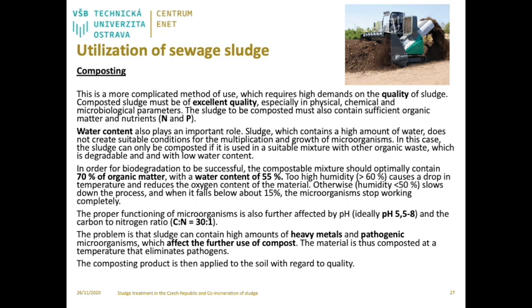Sludge, which contains a high amount of water, doesn't create suitable conditions for the multiplication and growth of microorganisms. In this case, the sludge can only be composted if it's used in a suitable mixture with other organic waste, which is degradable and with low water content. In order for biodegradation to be successful, the compostable mixture should optimally contain 70% of organic matter with a water content of 55%. Too high humidity causes a drop in temperature and reduces the oxygen content of the material. Otherwise, it slows down the process. And when it falls below about 15%, the microorganisms stop working completely.